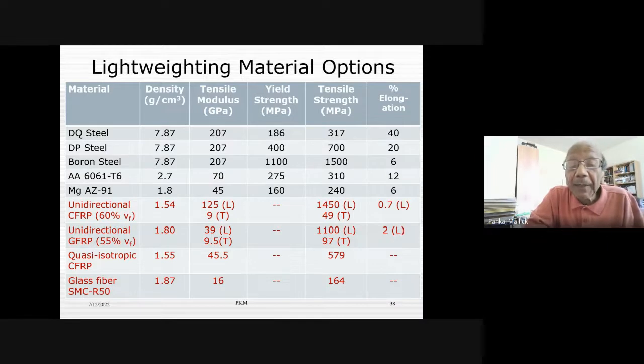But the good thing about this is that the modulus to density ratio of aluminum is the same as the modulus to density ratio of steels. So the interest in replacing steels with aluminum comes from the fact that it has a much lower density, yet it has the same modulus to density ratio.